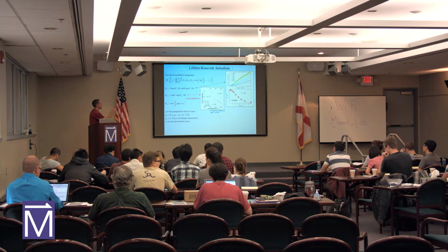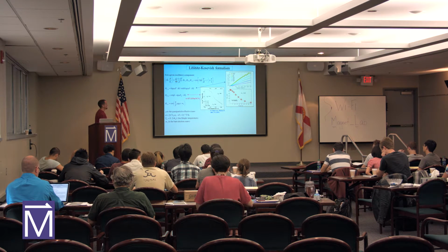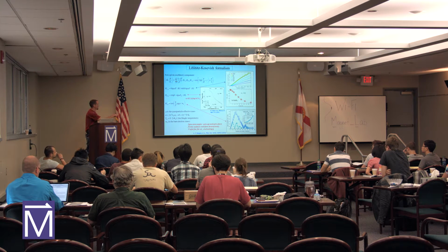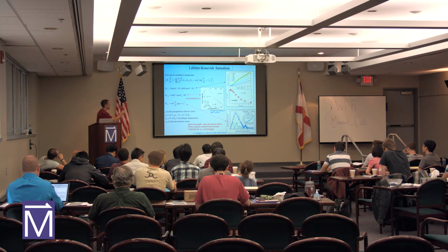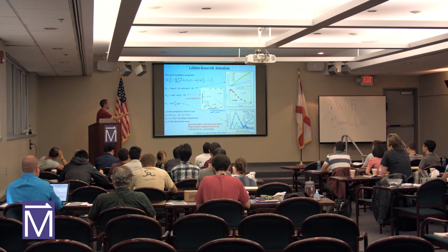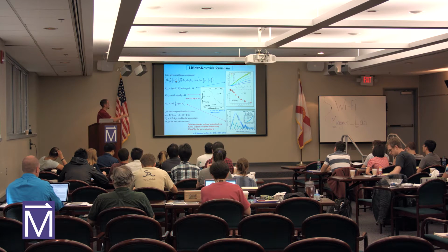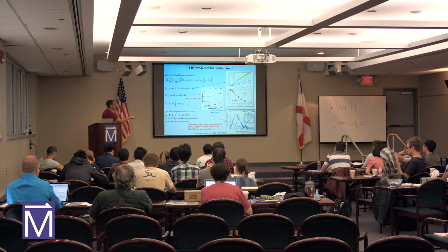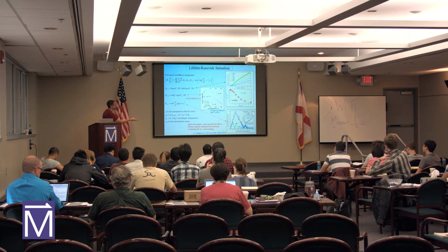Okay, so as we progress through, we know the effective mass. We know the Dingle temperature. The spin term takes into account that the up and down spin carriers have slightly different energies. So in this damping term, at some point this argument is going to be an odd integer, okay? Some constant, the g factor, the mass over the bare electron mass. When this equals 1, 3, 5, etc., we get cosine of pi over 2. And when that happens as you're rotating, you'll end up having the oscillation amplitude go away. We call these spin zero angles.